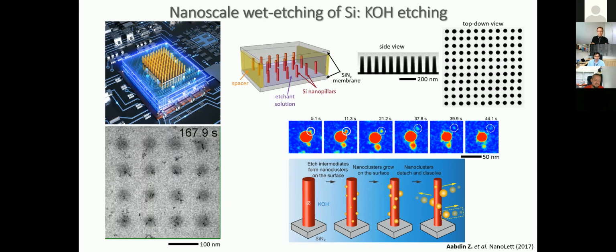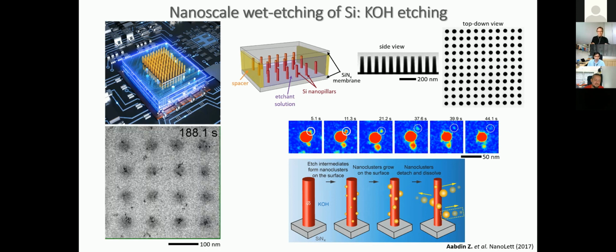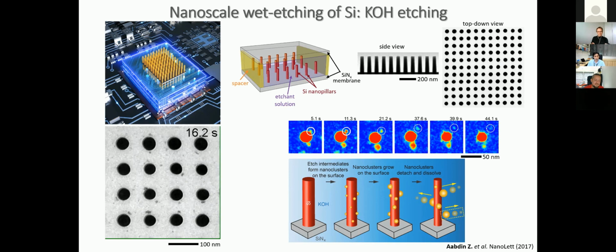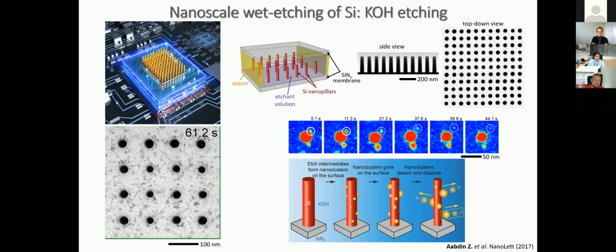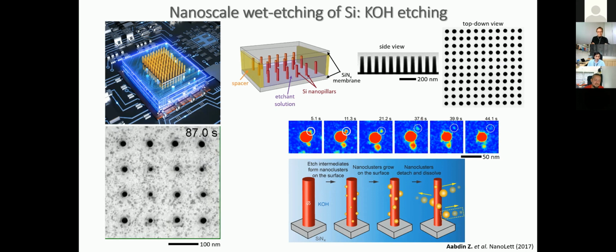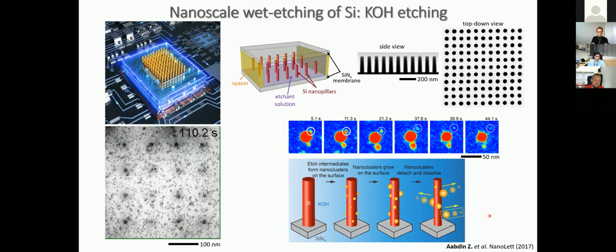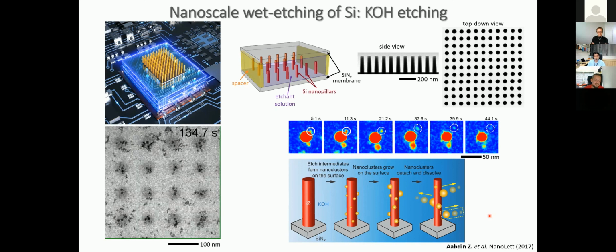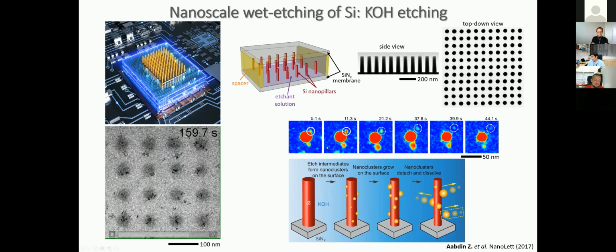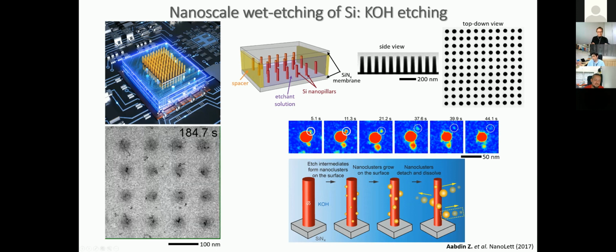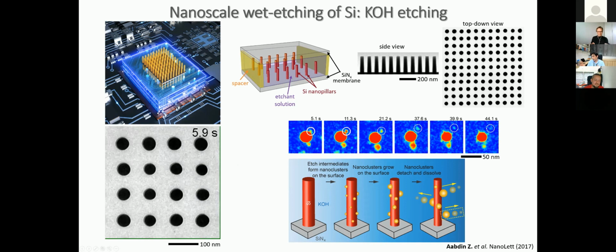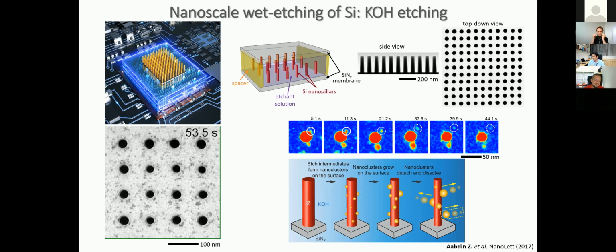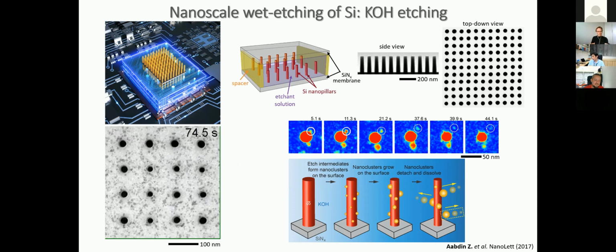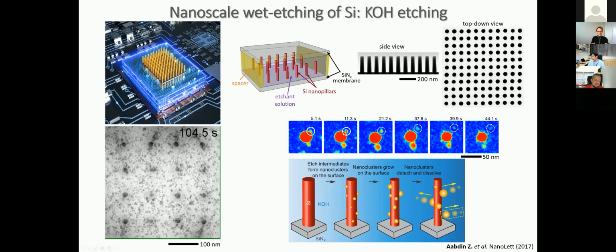I'm not going to go into what the forces are that are holding them together, but it has to do with the surface termination of the silicon during the etching in KOH. But these details you can find here. Once we understood this, we did these experiments. Of course, these byproducts are not good. Why? Because these byproducts limit the access of the etching. So it introduces a surface roughness, and you don't want this. Because if you want to build very small transistors, you want to have very full control over the surface. And if you have this, you just limit the access of etching, and you can start forming bumps on the surface.